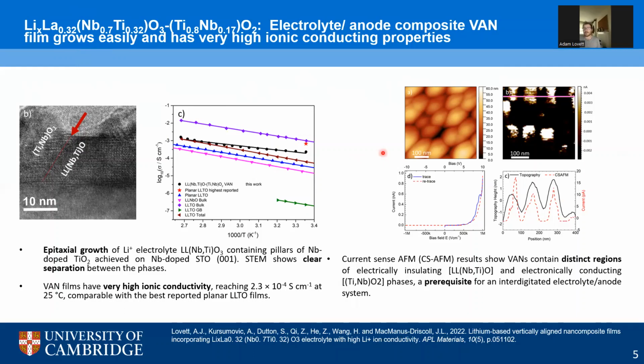We probe the electronic conductivity with current sense AFM. What is quite nicely seen in this AFM image is that the regions of high current correlate with topography, and in the context of our TEM, those are the columns of the electronic conducting niobium-doped titanium oxide. But the current remains quite low. And this is something that we learned and later correlated with this little thin film layer that grows underneath the column. This led us on to developing our second system, which you can find more out about on my poster.